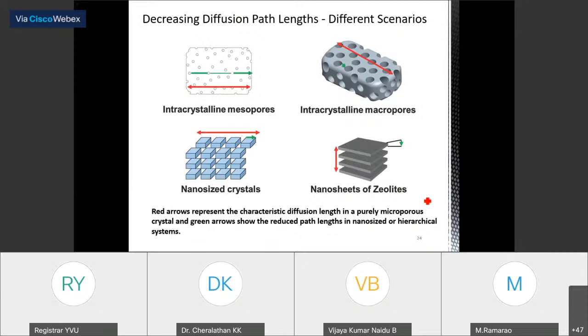That is what is shown in these different pictures. I have different scenarios. I have intracrystalline mesopores. You have to understand that if I say it has intracrystalline mesopores, it's a zeolite, so it already has micropores. In addition to that, I have these mesopores. In the case of conventional microporous zeolite, the diffusion path length is like this, shown by this red arrow. In the case of mesoporous zeolite, the diffusion path length will be reduced like this. In the case of intracrystalline macropores, the conventional microporous zeolite has a diffusion path length this much, and because of the introduction of these macropores, it has reduced to this much.